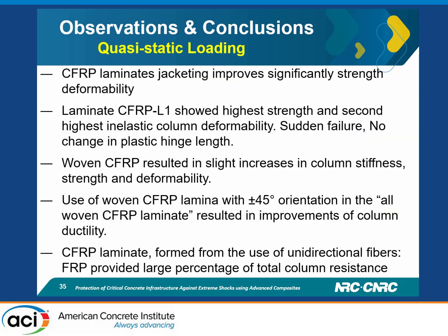So the observations here: when we are using the CFRP jacketing, a significant improvement in strength and deformability is observed, but it differs between layups. In the base layup, zero is the direction of the column, the main direction of the column. The 90 is the lateral direction. And when we use plus minus 45, the ductility is improved a lot. Then we studied different percentages between those three types of layers and different locations of the layup, and we concluded with one optimum distribution.